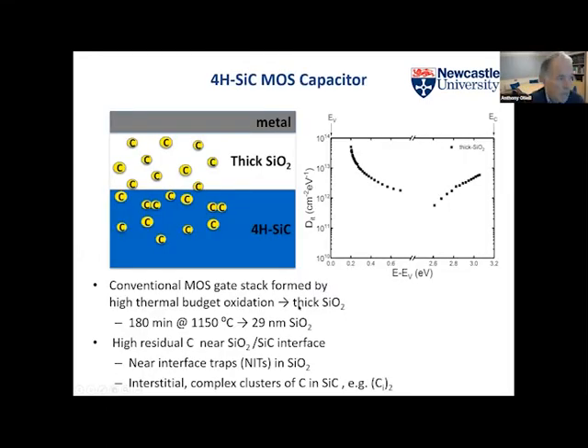So this is what I considered to be the problem when we came back to look at this. When you grow an oxide on silicon carbide, it's great that you get silicon dioxide, and it's one of the few semiconductors that has a natural oxide that stays where it's put. It doesn't dissolve in water or anything, it's silicon dioxide. However, it's just silicon dioxide. The carbon isn't or shouldn't be in it, and some of that carbon can get away in gaseous form, carbon monoxide, carbon dioxide, but some of it is going to remain, and the more oxidation, the more carbon is going to be there.